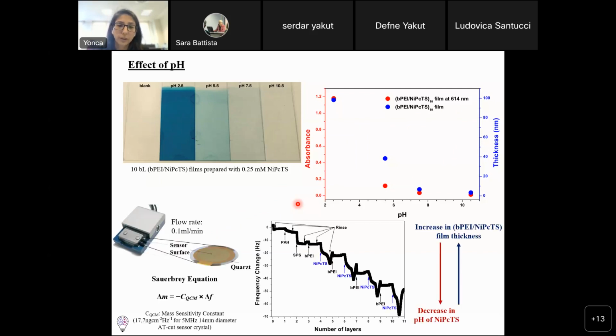So actually, in order to monitor the molecular deposition in real time, there is a pretty good technique, the quartz crystal microbalance. And by using this technique, you can actually deposit your film and monitor the deposition in real time. So here you have a quartz piece sensor, which is coated with gold. And on top of it, you introduce your materials one by one in a sequential order, as we did in the standard layer by layer study. And then you can monitor the change in frequency. So PEI and PSS represent the adhesion layers. The BPEI is our very first positively charged layer.